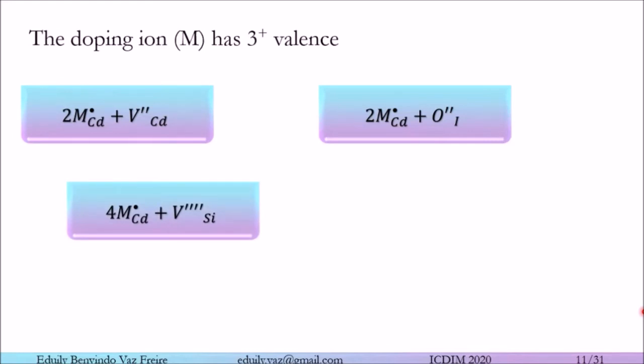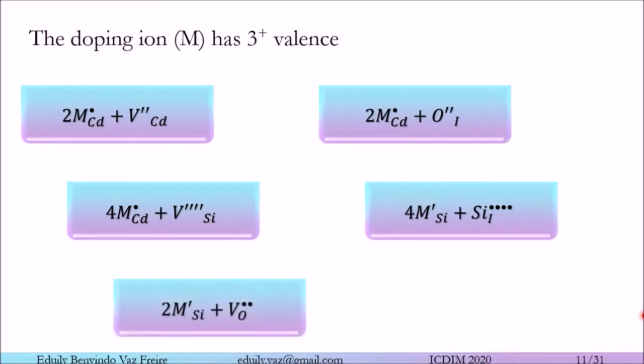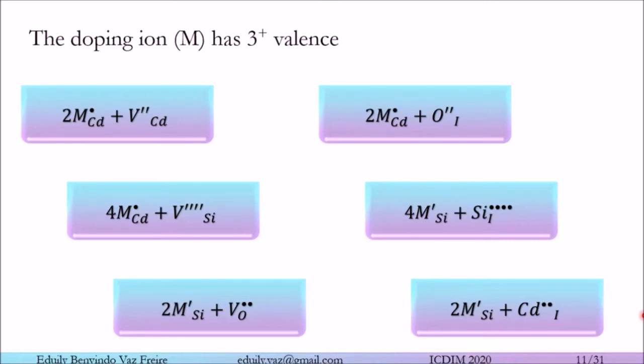The third way is to place 4 doping ions at the cadmium sites and to compensate the charge with a silicon vacancy. The fourth way is to place 4 doping ions at the silicon sites and compensate the charge with an interstitial silicon ion. The fifth way is to place 2 doping ions at the silicon sites and to compensate the charge with an oxygen vacancy. The sixth way is to place 2 doping ions on the silicon sites and compensate the charge with an interstitial cadmium ion.